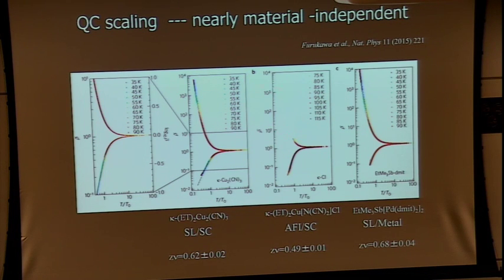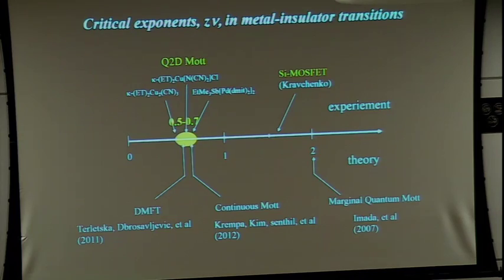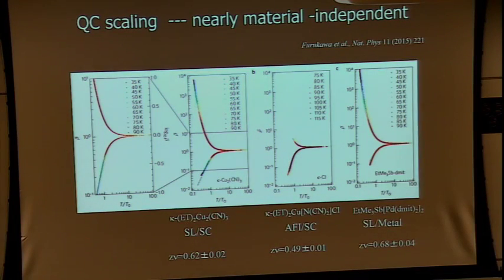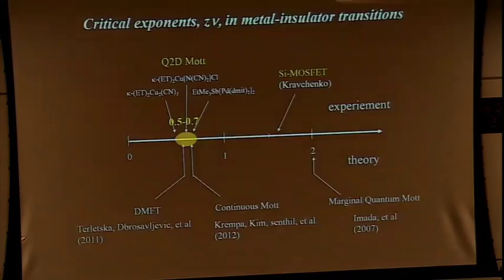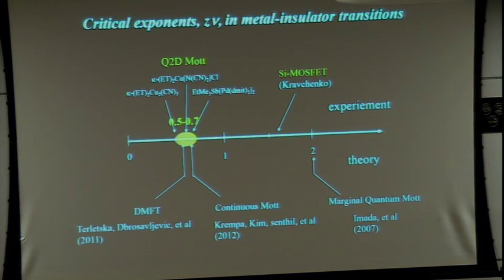And the data is missing here because this is located very close to the Mott transition boundary. So we cannot access the negative pressures. So data is missing here. But anyway, all of the materials show nearly the same quantum critical behaviors. And the Z nu value, the exponent for the three materials, is located around here, 0.5 to 0.7.